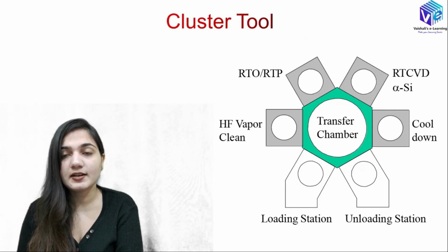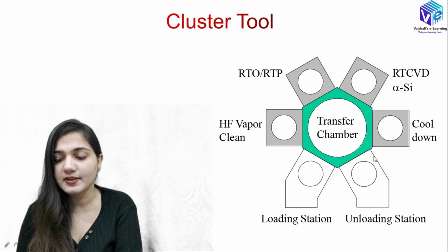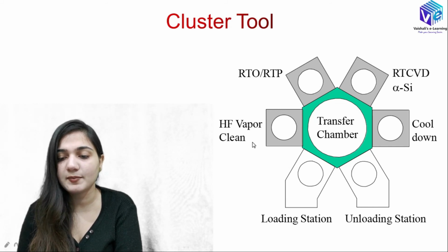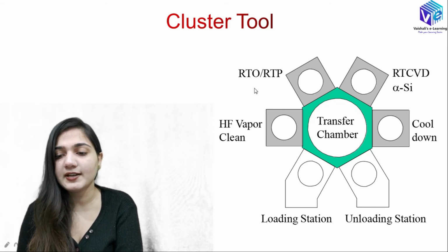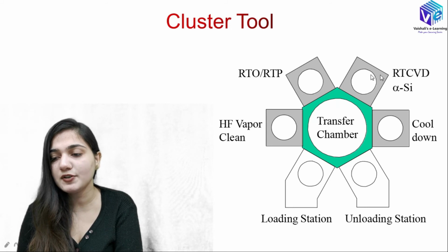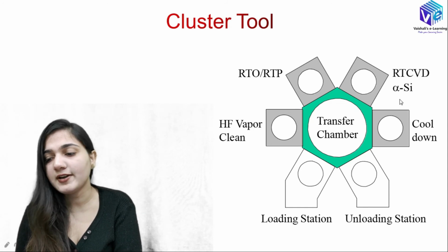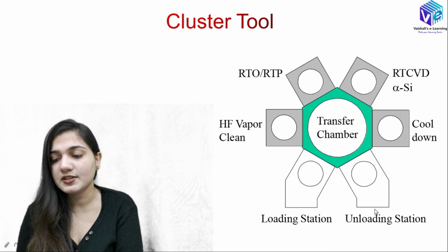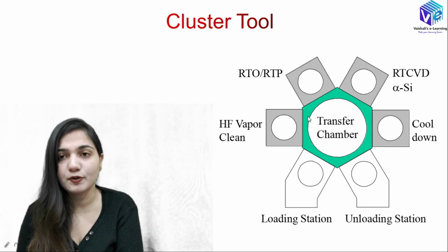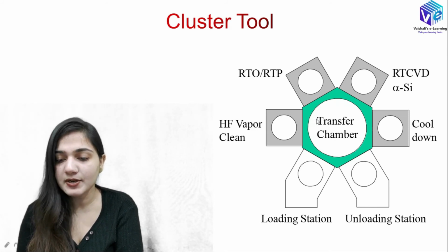So you can see the cluster tool. Here we will be having the loading station. After that we will be having HF vapor clean. So first I will be doing the in situ vapor cleaning. After that I will be having the RTO or RTP process. Then I will be having the RT CVD processing, where I will be having the actual deposition. Then I will be having the cooling down and unloading station. So all of these are robotically controlled chambers.